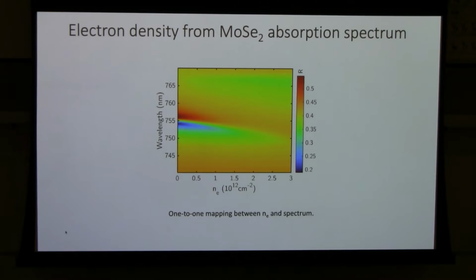Yes. This is reflectivity in absolute units. You've got R at 0.5. You have a single layer of electrons making that much reflectivity? Yes, so I need to double check this, but I can tell you that with a single layer sitting on a substrate, because the exciton oscillator strength is really strong and also very sharp, it can indeed create a reflection change of 50%. So maybe this is more like delta R over R. But people have shown that if you put it on a metal, a monolayer can actually absorb all the light, just because the oscillator strength is very, very large for these monolayer TMDs.